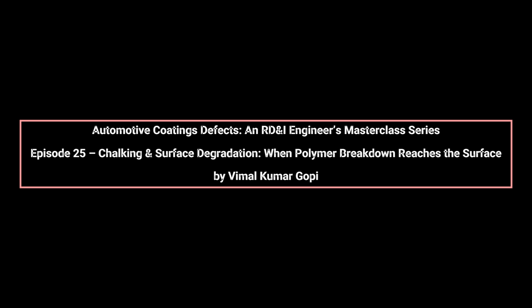Curing quality strongly affects chalk resistance. Undercured coatings retain unreacted groups that oxidize easily, accelerating degradation. Overcured coatings develop high internal stress and microcracks that increase oxygen and moisture diffusion. Both conditions shorten the time to chalking.